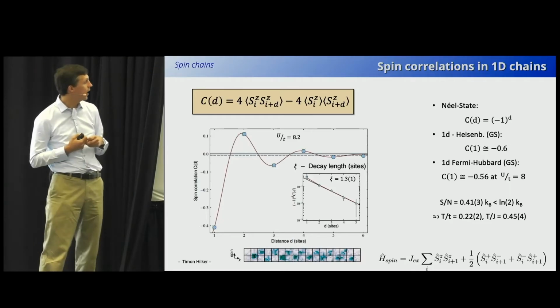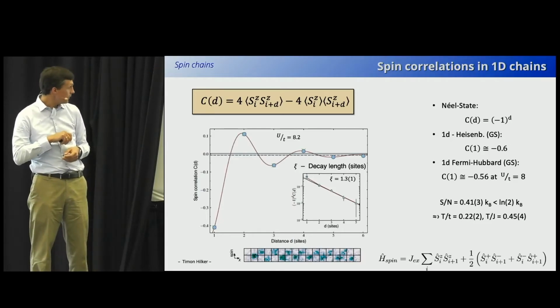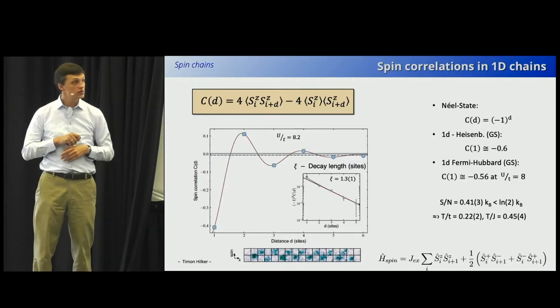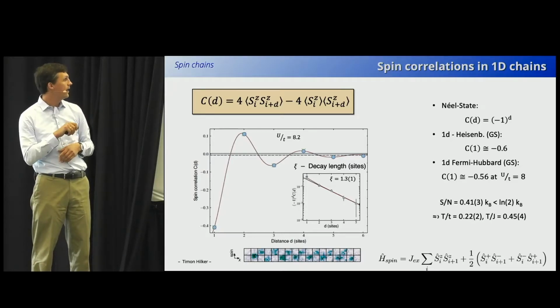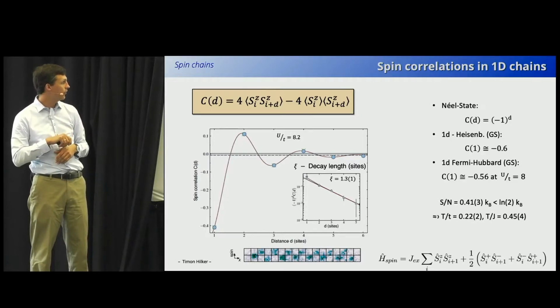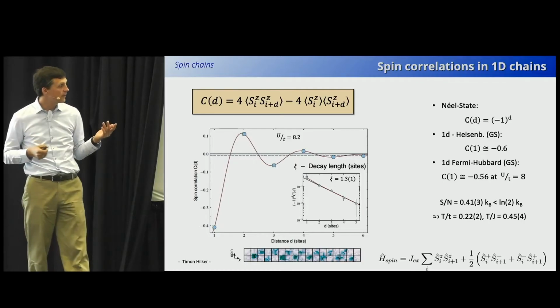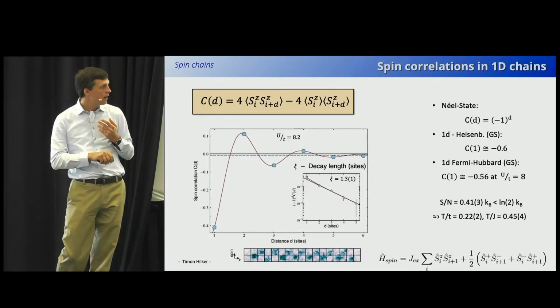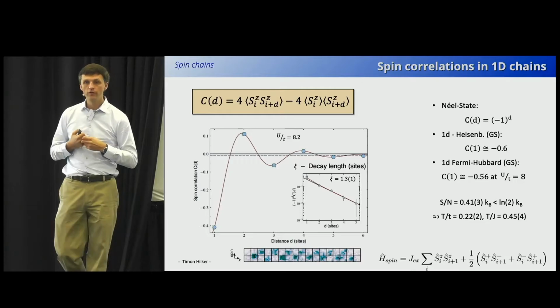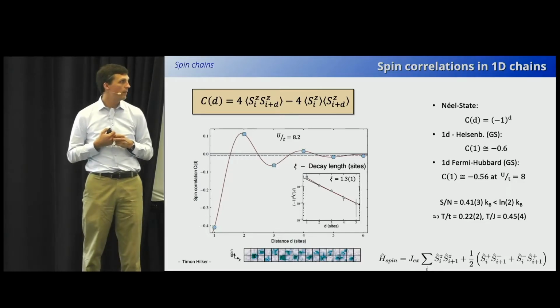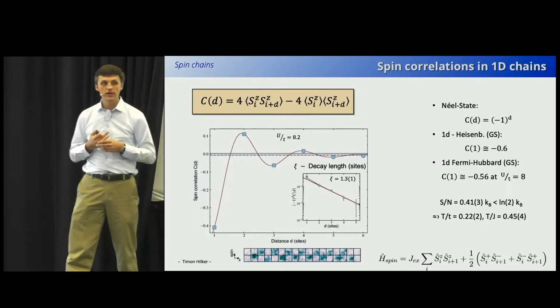And then one can run these statistics. So here's an example in 1D. One finds very strong nearest neighbor correlations, but then a very fast decay. And this corresponds very well to the theoretical expectations at temperatures around 0.2 of the tunnel energy, or about half of this exchange energy J.